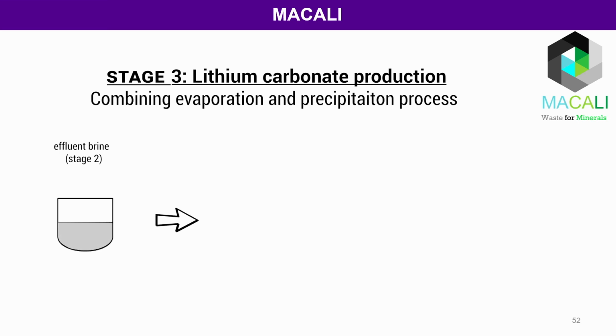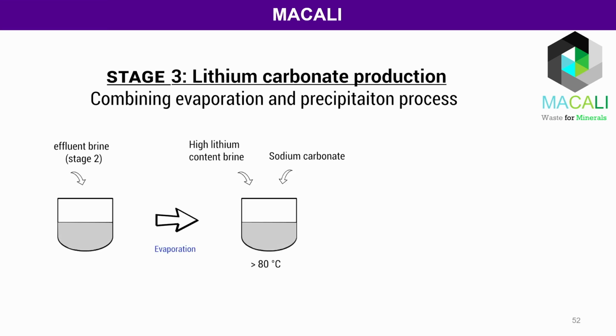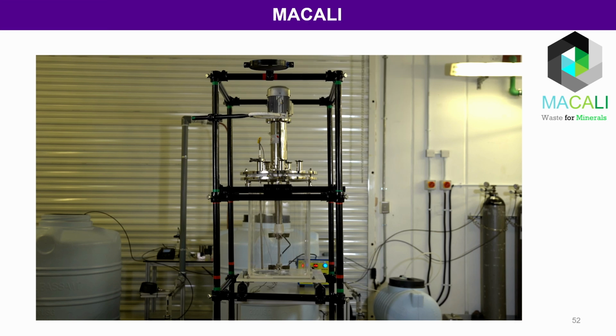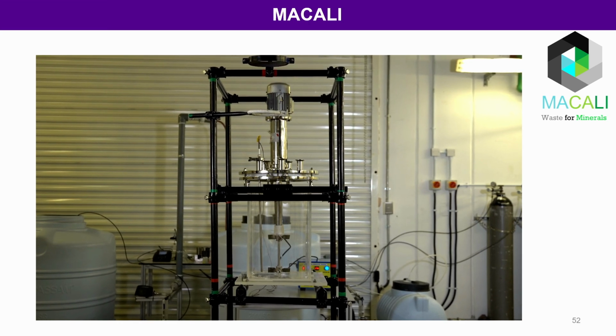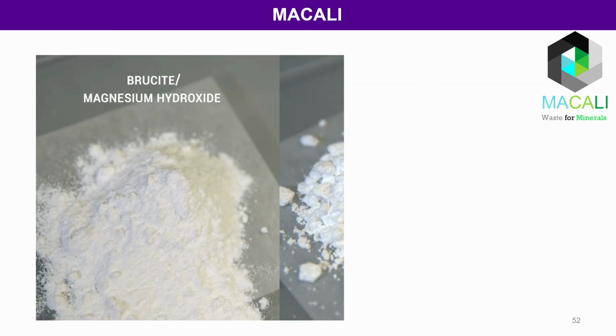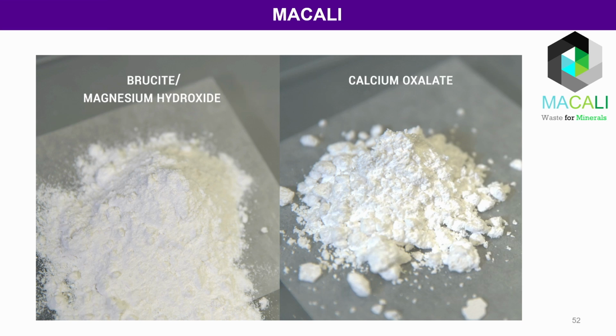The evaporation process is required to increase the lithium content in the brine. Sodium carbonate could then be used to precipitate lithium carbonate from the high lithium content brine at reaction temperatures above 80 degrees Celsius. Our prototype successfully demonstrates the technology for producing brucite and calcium oxalate.